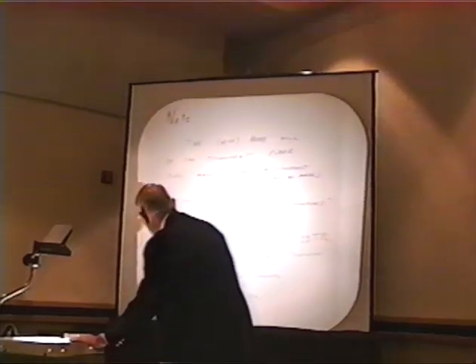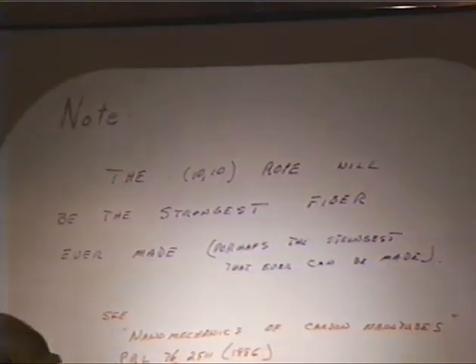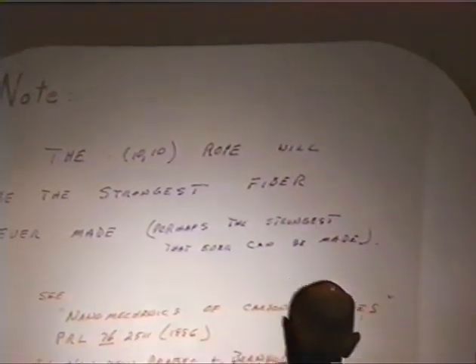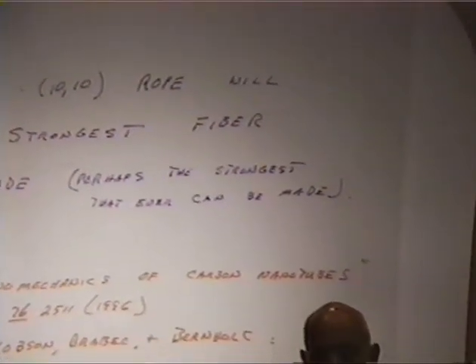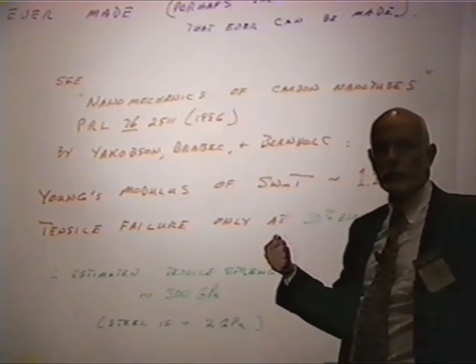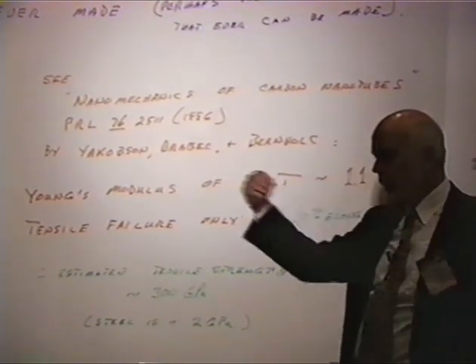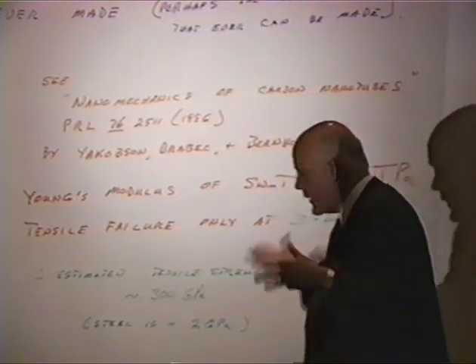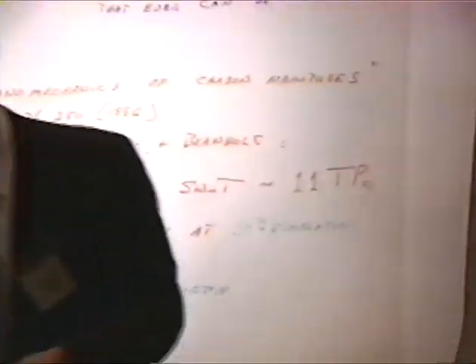As I mentioned, it does, in simulations, appear to be incredibly strong. There is an indication that we may be able to pull this tube to 20 to 30% elongation before it finally fails. And when it fails at even 30% elongation, it doesn't fail by brittle failure, but rather by plastic pulling on threads. That would give us a tensile strength something like 300 gigapascal or so. Easily the strongest fiber that had ever been made.